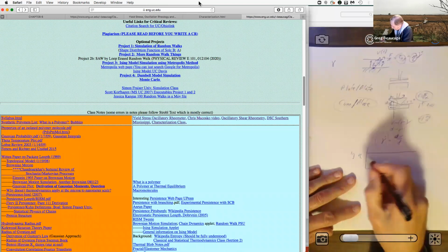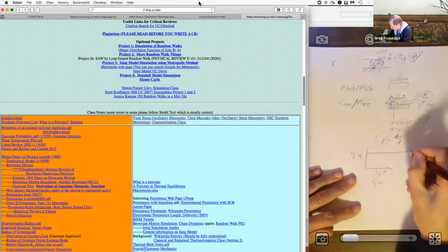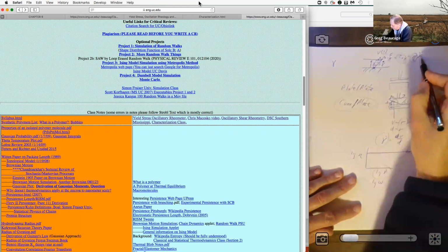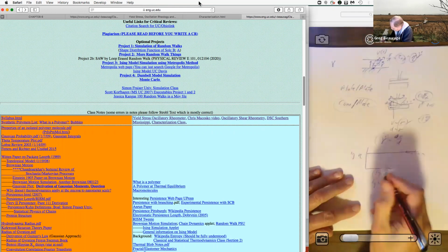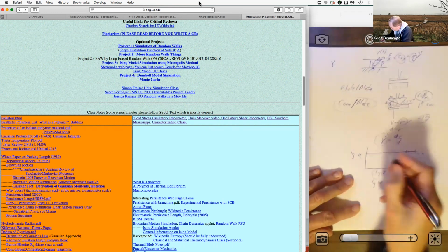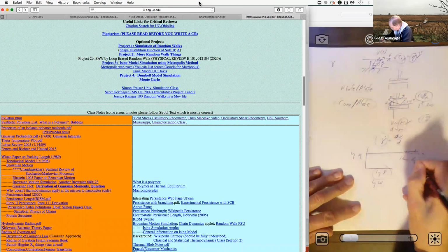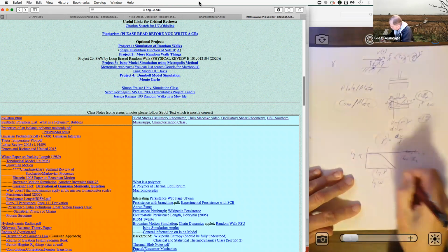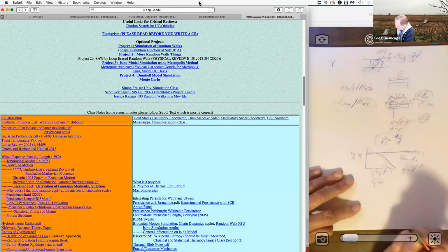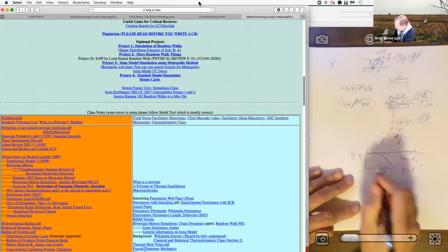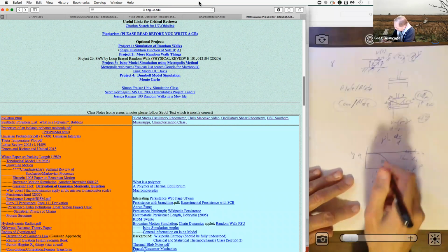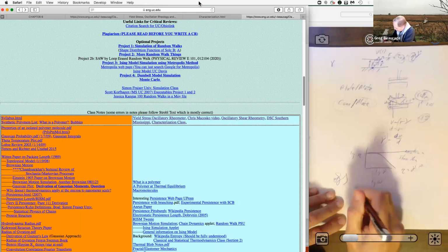If it's a Newtonian fluid, like water, then this is just flat. It doesn't change viscosity. The force is proportional to the motion, and it's linear. But if it's a polymer fluid, a shear thinning fluid, then this drops. It follows a power law, it's log-log: the viscosity goes as the strain rate to a power. And that again is because the structure of the material changes. Say you take a polymer coil and you deform it, and then it can go back.